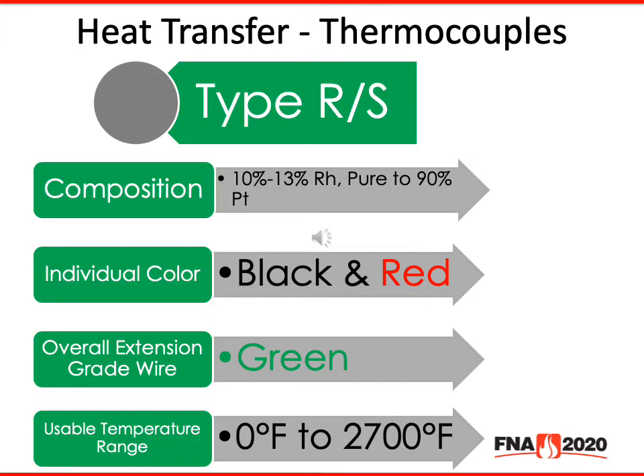Another common type is type R or S. Composition is 10 to 13% rhodium and then pure to 90% platinum. Individual colors are black and red. Overall extension grade wire is green. Usable temperature range is 0 to 2700 degrees.